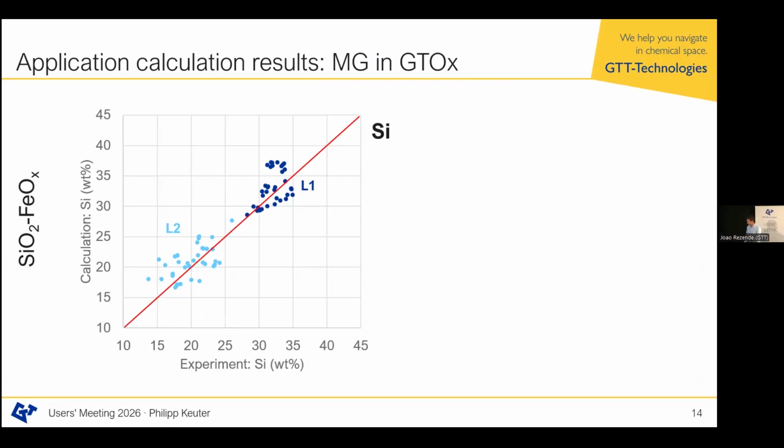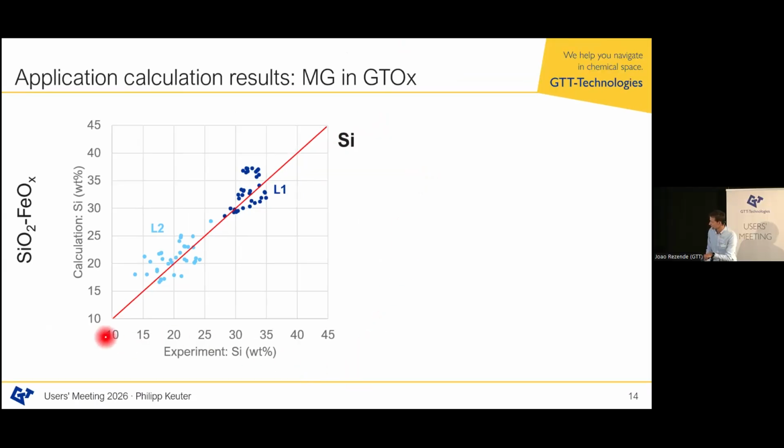different composition and temperatures, and what we can investigate for, let's say, one element, for silicon, how the silicon concentration in the experiment differs compared to the calculated one. So red is full agreement, and then we see the silicon concentration between the different liquid mixtures upon phase separation, and then we can compare how well that is in line with the experiment. Trend-wise, you already see that this looks quite good. Sometimes quantitative agreement is better, but overall, this already looks quite promising.